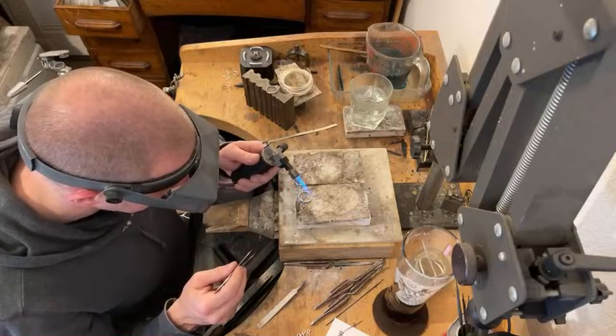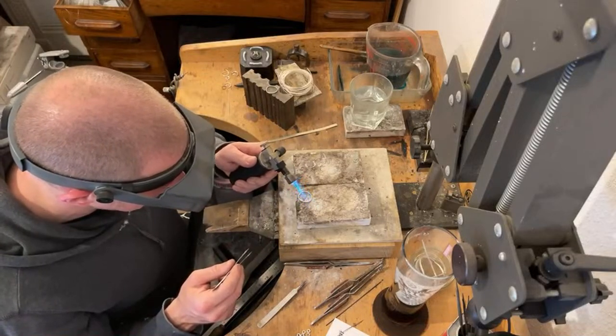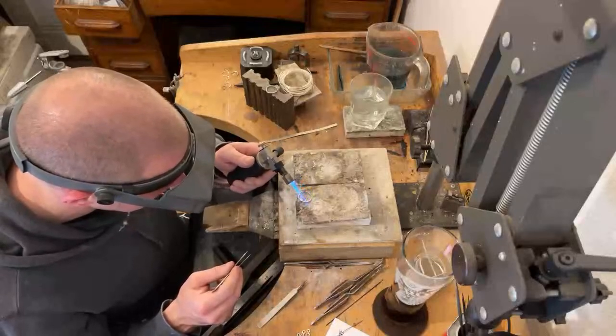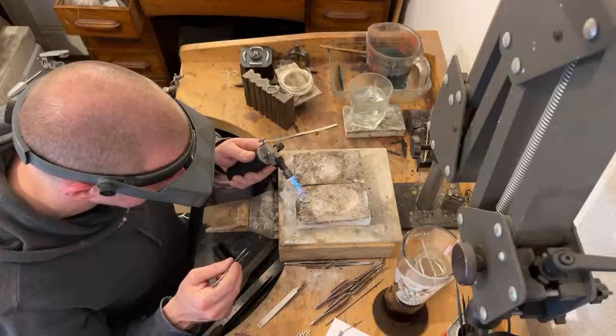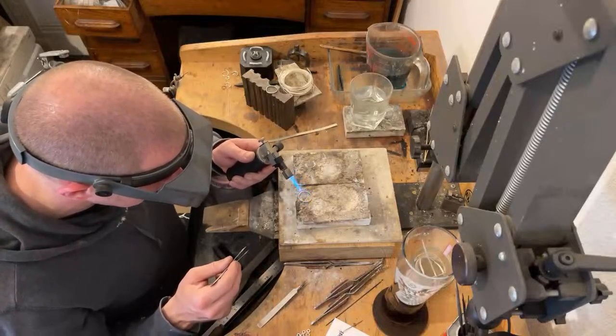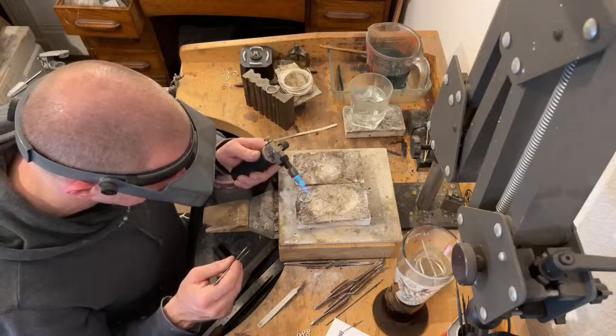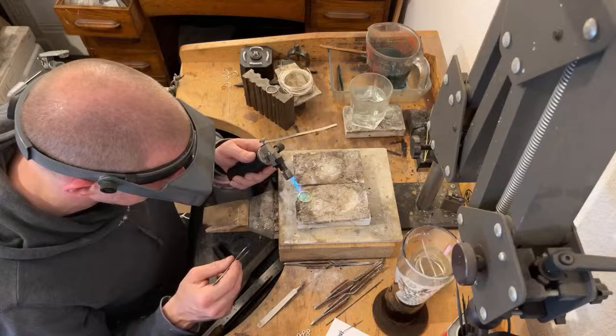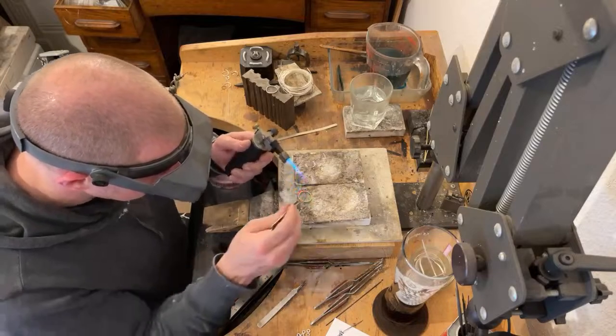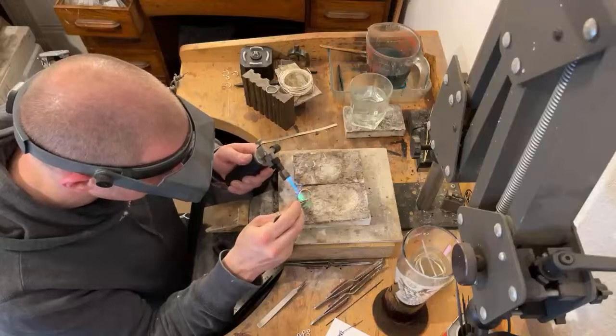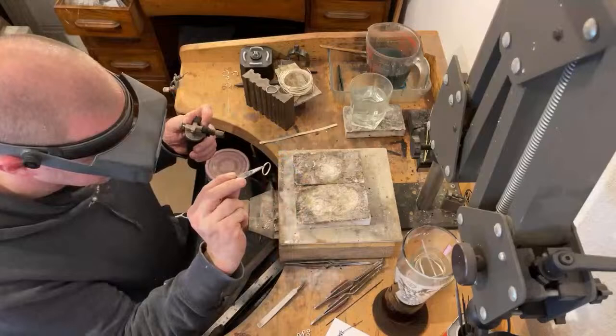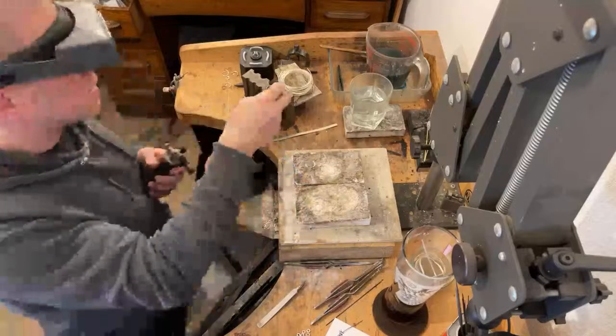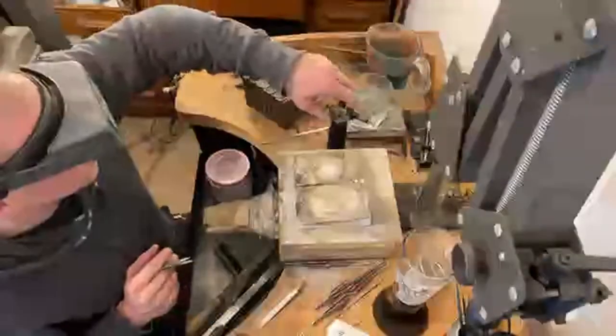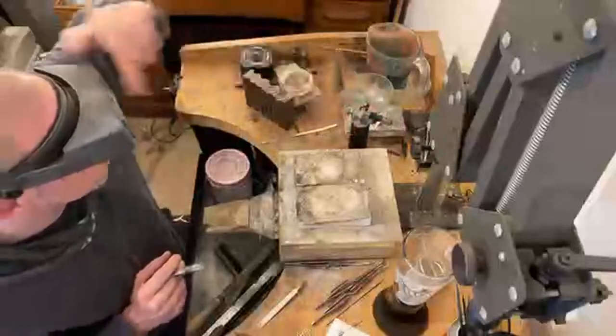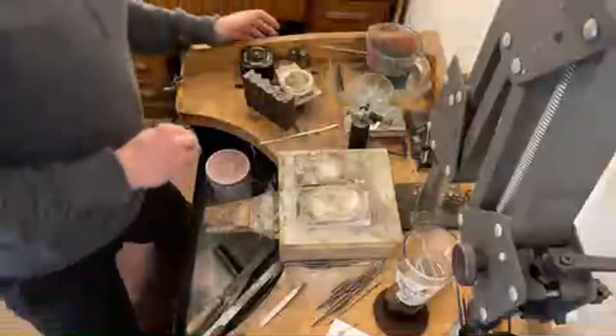Yeah, in the process of making the wire, I discovered that quenching sterling silver is problematic. I've not had the problems quenching solder jobs, but it caused a lot of problems making ingots and then wire. I don't think it's that the problems don't exist when you're quenching solder jobs. They just don't manifest themselves, because you're not doing too much work to the metal, it's not being rolled out or drawn out. You don't get the blistering, for one, but the porosity must still be there to some extent, so they could be taking on board water. But it doesn't.